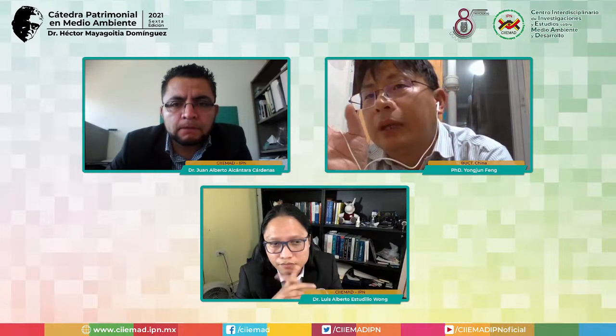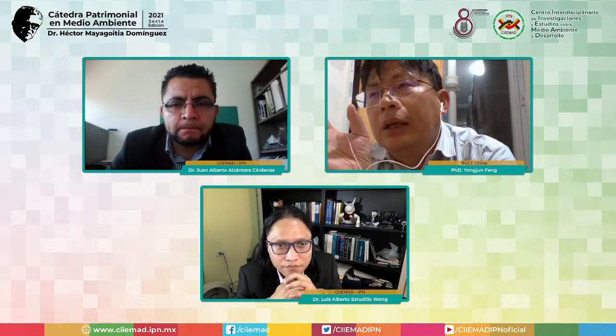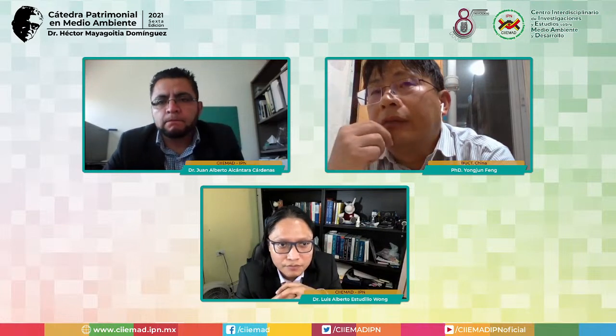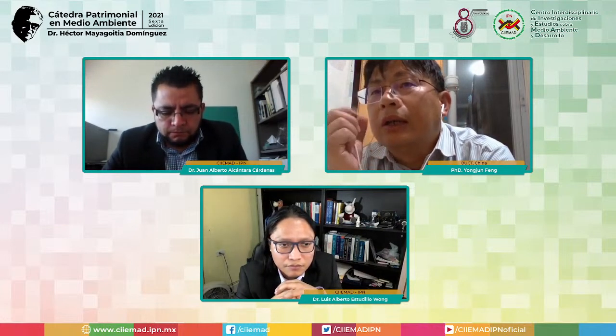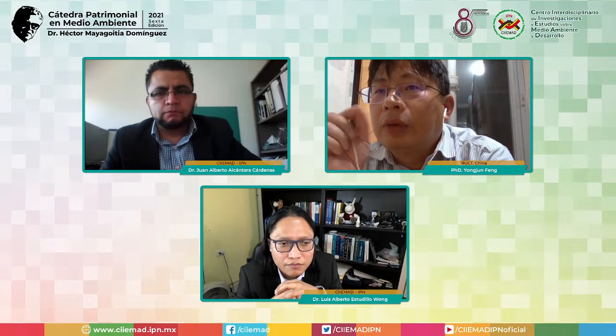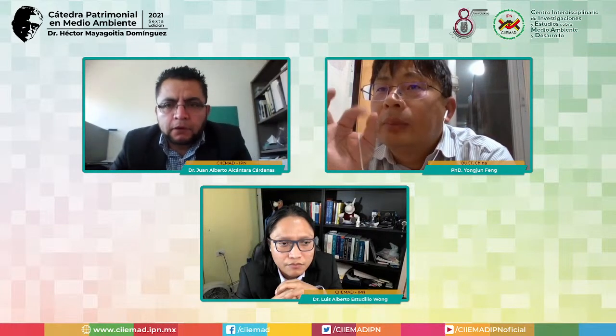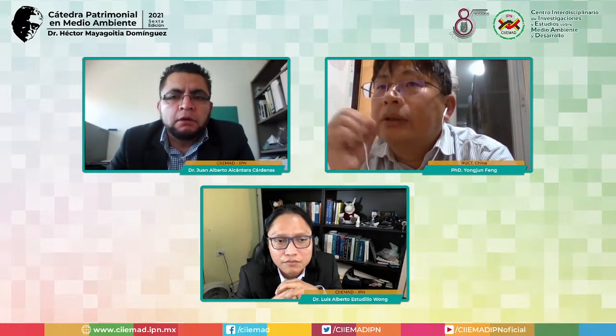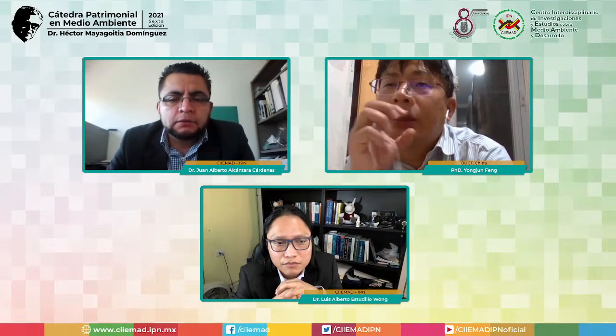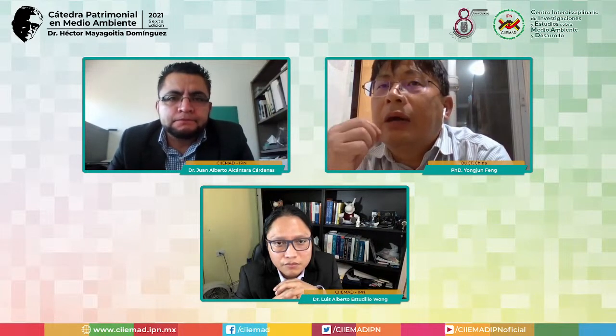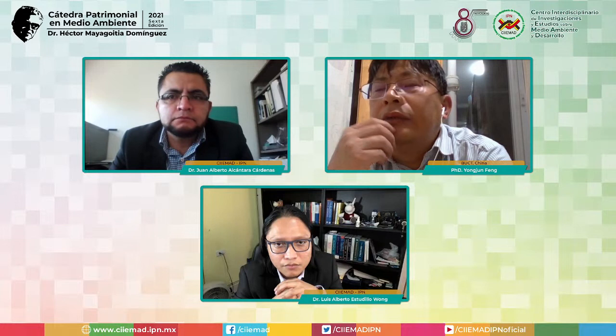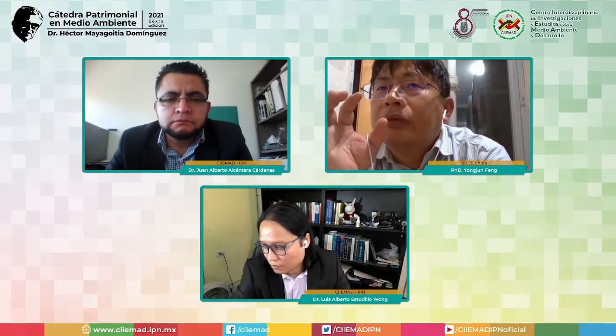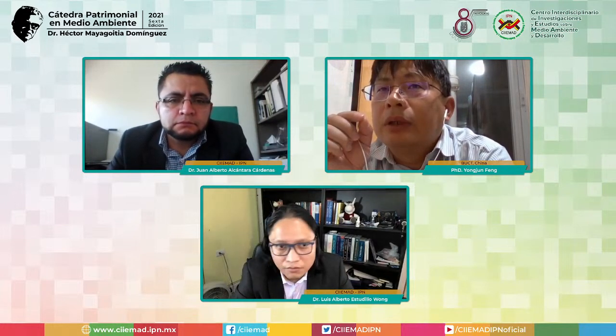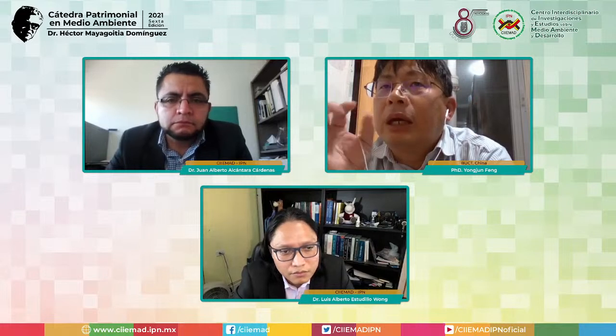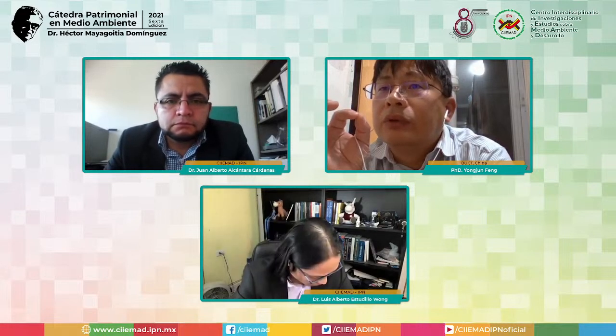So we can choose different metals. For example, nickel iron: one is divalent, one is trivalent. The metal and the anions in the whole sheet are the ones that we can choose and change. But from the literature, we can say the nickel iron LDH is almost the best one for the oxygen evolution.